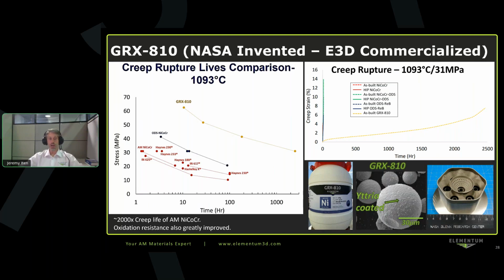This alloy is exceptional for extreme environments. Creep performance is amazing compared to other nickel superalloys, for example. And you can see that compared to some of these other materials that are relatively good in creep, Inconel 625, Haynes 230, Haynes 233, 188, Inconel 617, Hastelloy X, and even a nickel cobalt chrome oxide dispersion strengthened alloy there in the dark blackish colored dots and dash line. Now the GRX-810 in the yellow on the top, that's showing that the creep performance really is exceptional compared to these other options. GRX-810 is a nickel cobalt chrome based alloy, but there's other alloy additions to that. And then there's also a nano yttria oxide dispersion within that alloy.